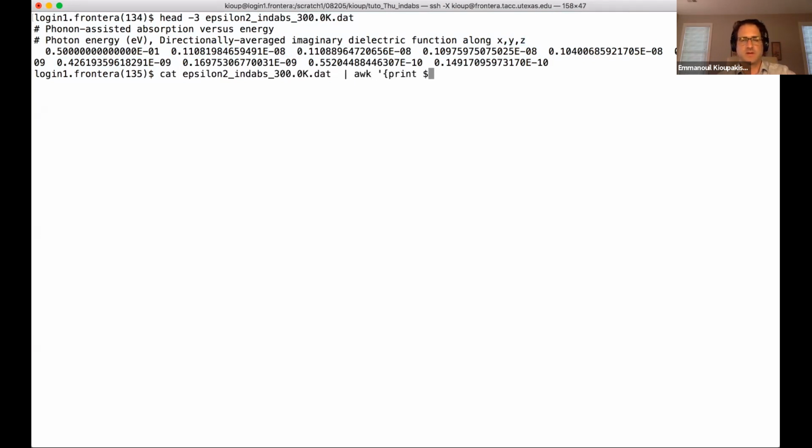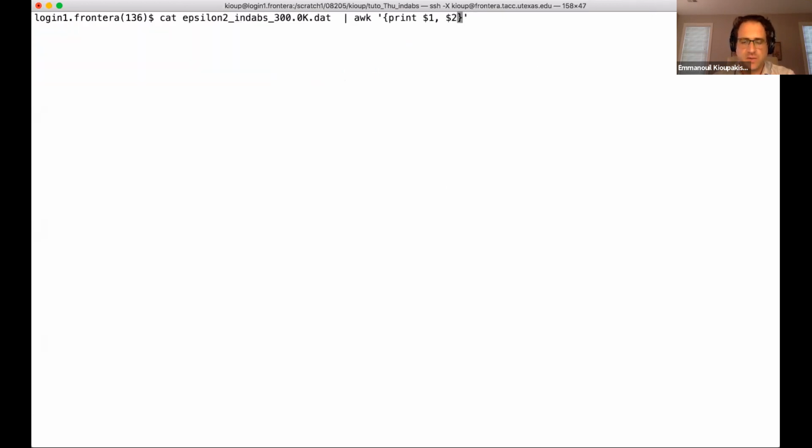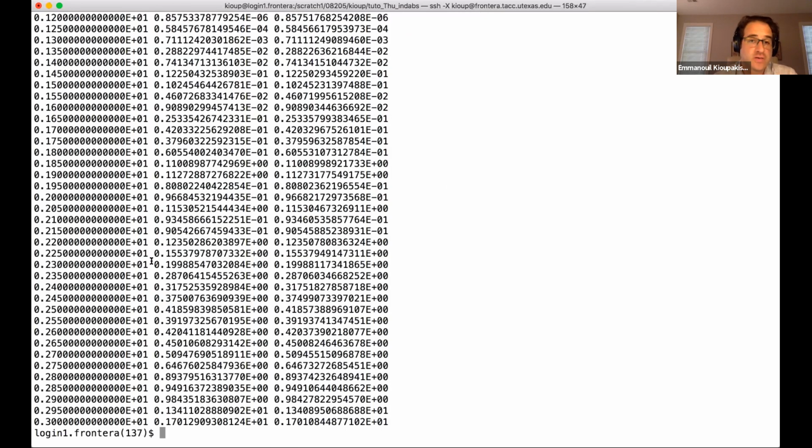let's print just to see the first two data points. So here's what you would see. Say if you use it for the first broadening, the photon energy, and here's the broadening parameter. Let's look at two different broadening parameters, I use 1 meV or I use 2 meV. Do I see a difference? As you see, I should not see a difference. And indeed, look at the situation here, the values are almost exactly the same. That's what should happen. It means that the imaginary broadening parameter does not affect my results. That's a good sign.